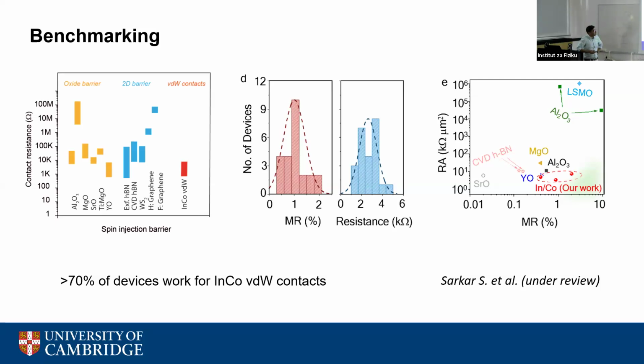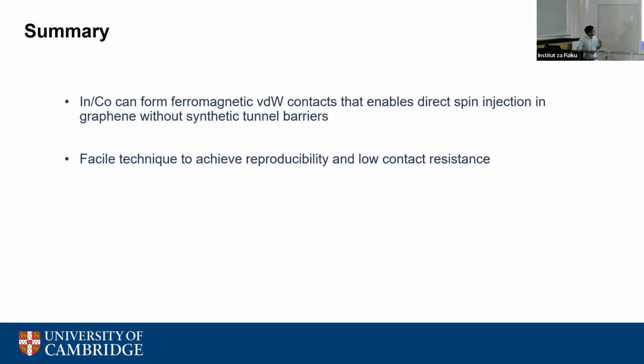And we obtain MR, which is not obviously record high, because people have shown using LSMO and other materials with very high spin polarization that you can introduce higher magnetoresistance. But again, the contact resistance is very high, which is practically not feasible. So we have a sweet spot where we have decent, reasonable MR, which is quite consistent with previous reports, but also low contact resistance. To summarize, what we can show here is that we can use these van der Waals contacts to enable direct spin injection without tunnel barriers that are really hard to grow on 2D materials. And this is a facile technique to reproducibly achieve spintronic devices with low contact resistance.